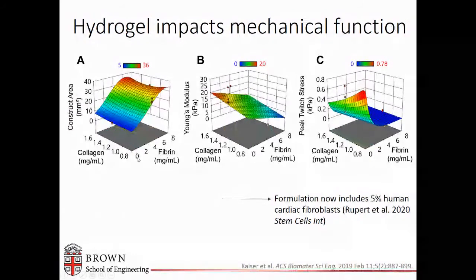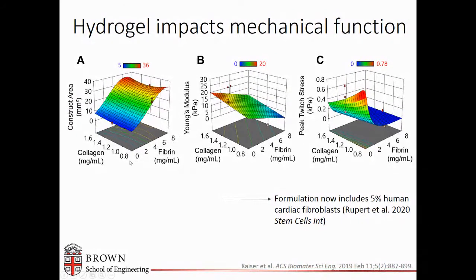You can see here that the low fibrin concentration or no fibrin gave us the greatest compaction in the tissues, or the smallest construct area. And when we measured mechanics in these tissues, the stiffness was highest in the zero fibrin group. You can see the points that we measured are in red, and the surface is the model that fit the data. The force that we measured, or the peak twitch stress, was maximum also along this edge. But contrary to stiffness, which was highest at a high collagen concentration, the peak twitch force was predicted to be highest at a lower collagen concentration.